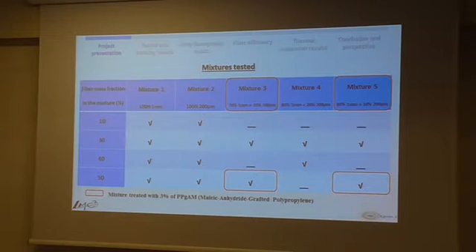In this project, several mixtures were prepared using a combination of the two types of fibers, the 200 microns and the 1 millimeter. I chose to present these 5 mixtures in this presentation. For mixtures 3 and 5, for example, with 50% fiber rate, we added a compatibilizer, which is the PPgAM, in order to see its effect on the mechanical properties and on the adhesion between the fibers and the polymer.